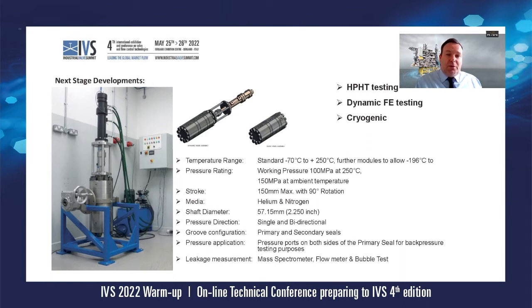So we are aware that we need to do more to replicate real conditions in an actual valve to prove durability and long-term effectiveness of our selected seal arrangements in real-life valve applications. And last year, we did a further upgrade to our existing test capability and added much more functionality to our stem seal testing. We've expanded our test vessel so it can take a slightly larger stem seal and different stem arrangements. We've attached an actuator to the rig, allowing for both linear stroke and a 90-degree on-off oscillation. And of course, the vessel is now capable of taking pressures up to 100 megapascals with a new gas booster installed to help us on that.